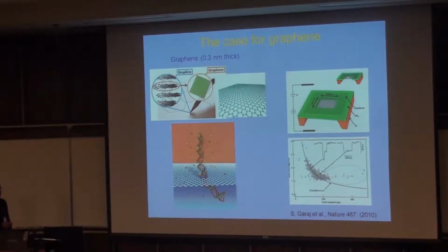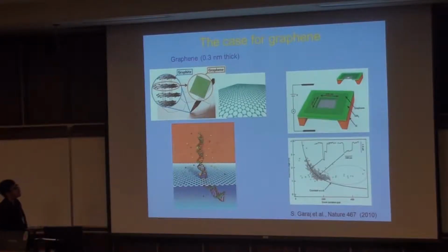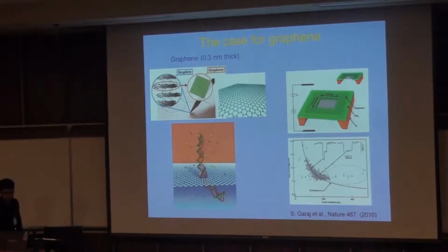Normal solid-state nanopores are at least a few nanometers wide, so the resolution is limited to a few nucleotides. But with graphene, we can sample on the individual nucleotide basis. In addition to that, graphene is electrically active, meaning that we can pass a current through it. We can control the carrier concentration within graphene. So hopefully by using graphene as the nanopore membrane, we can do some additional tricks to try to sense this DNA.